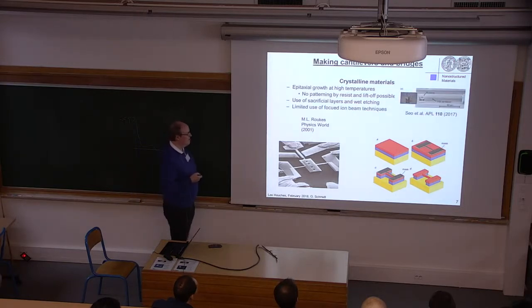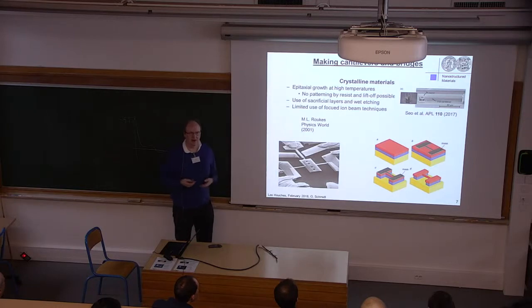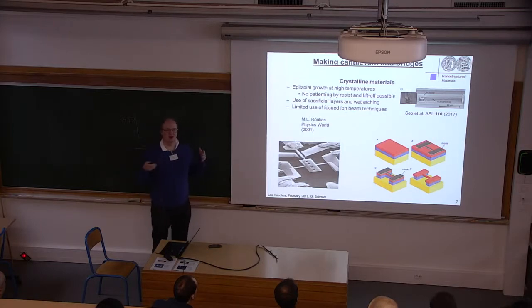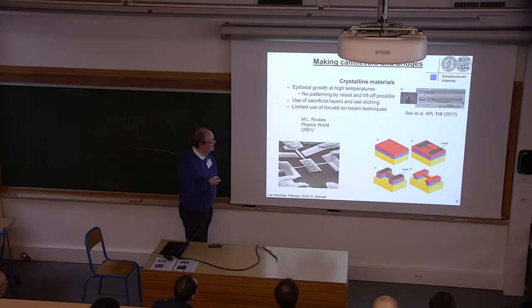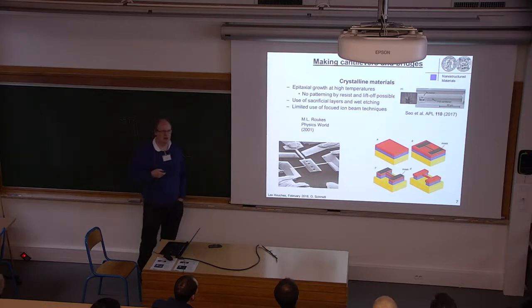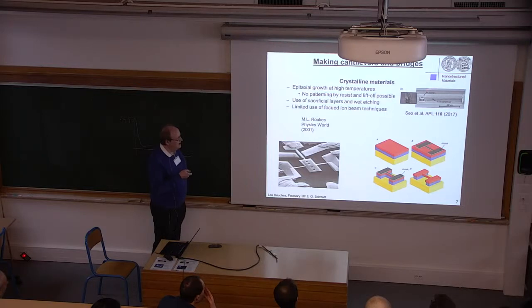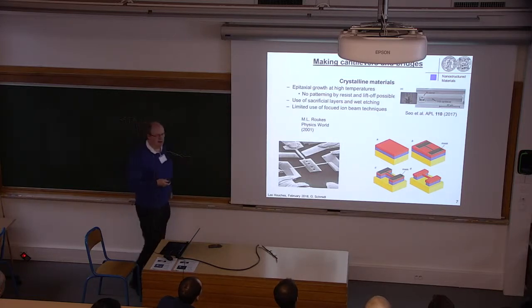You can also use focused ion beam. It's quite clear you can do it, but the use is limited, because you're always restricted to certain shapes, because you are still coupled to the substrate, and that means somehow you have to etch from the side. There has been one result from the Seo group, but you can see this resonator had about 80 micron length, and the resonance frequency was in the kilohertz range, upper 100 kilohertz range, but still not at all what we want to go for. And again, you see, if you do it by focused ion beam, then you get this pit underneath. And for future integration, this pit is not very useful, because you have to go over the edges. And so you want to do it in a different way.